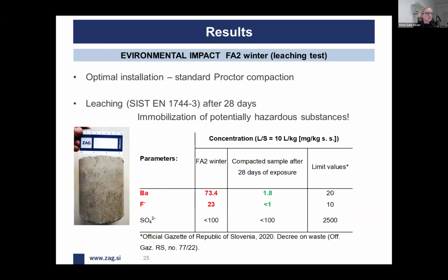The further step was to prepare the geotechnical composite according to the standard Proctor compaction test and perform the leaching test on the composite, which was prepared from the original ash. The results showed that the concentrations of barium and fluorine, which were exceeding the limiting values in the raw ash, here were below the limit. We can assign this to different factors, such as hydraulic activity of the ash and, of course, lower permeability of the material prepared by the Proctor compaction procedure.